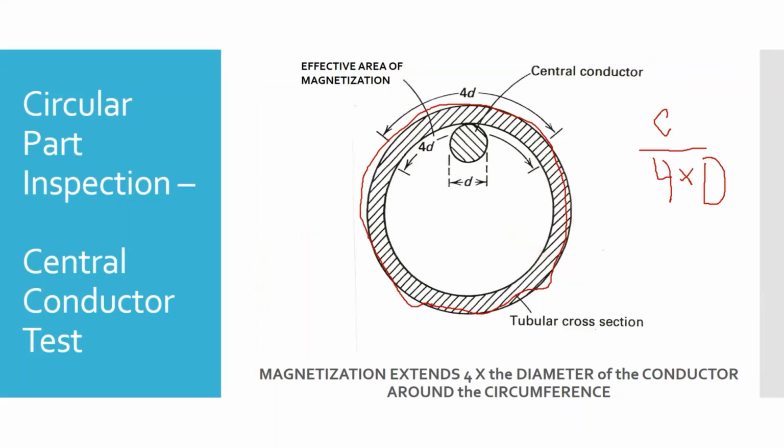What do you think? 3 or 4? You have to do it 4. You always have to round up, okay? Because you want to have some overlap so you don't miss it. So, that calculation you can do. So you'd have to turn it 4 times.